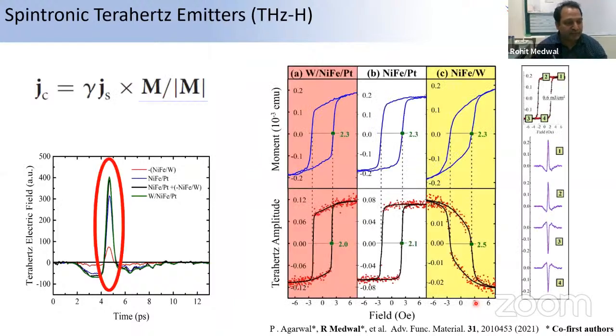If I record this pulse, especially the terahertz field, as a function of the M, which I can control by applied magnetic field, I can really see the hysteresis loop, which is generally observed from VSM, or vibrating sample magnetometers. So the MH loop we generally measure from the VSM, or MOKE measurement is also very common. But we are able to do the same experiment by mapping this terahertz electric field as a function of the magnetic field.